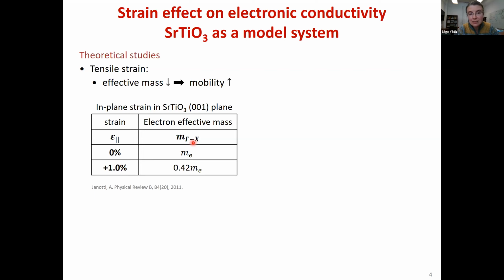And the question is, when this thin film strontium titanate is in the device, which sustains strain, what is the resulting change in the electronic conductivity? And there are a few previous studies that have attempted to look at this. And theoretically, the first prediction that we see is that under tensile strain, the effective mass of the electrons goes down, which should increase the mobility and therefore the electronic conductivity.